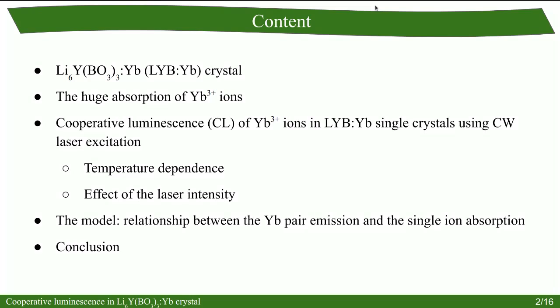First, I will show you the lithium-yttrium borate crystals, the physical properties and the growth technique. After that, I will present the absorption spectra of the ytterbium ions in these crystals, and I will demonstrate the huge absorption of these ions in this host. After this, I will show you the measurement of the cooperative luminescence of ytterbium ions in lithium-yttrium borate crystals using continuous wave laser excitations, and also the temperature dependence and the laser intensity dependence of the CL spectra. To understand the experimental results, I will demonstrate a model which is based on the relationship between the ytterbium pair emission and the single ion absorption.